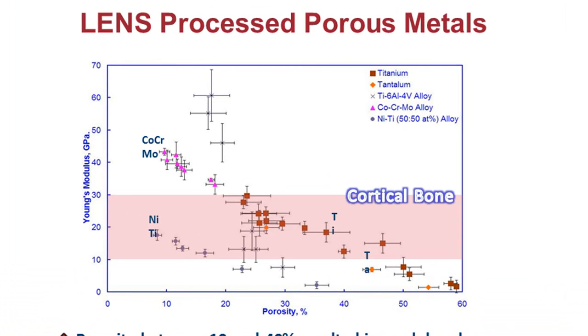This is a nutshell of a variety of porous structures we've worked on over the years, from titanium to tantalum to Ti64 to cobalt chrome moly to nitinol. These are all materials widely used in the biomedical device industry, and the point is, regardless of the material and its density, we can bring down the overall modulus of all of these materials to within the bone range.